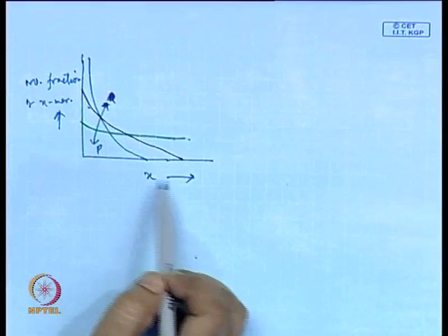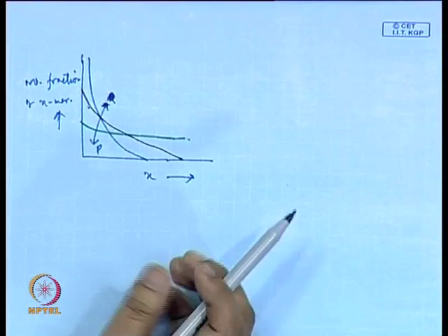So, if you take a polymerization mixture at the end, the maximum number present are the monomers, then dimers, then trimers and so on. So, the real polymers would be in the smallest number present in the reaction medium. But numbers are not always very significant, weights are more significant than numbers. So, we will look at how the weight fraction of the individual chains varies with x, which is the number of monomer units present.